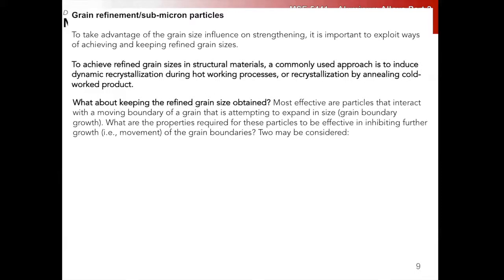It recrystallizes by what's called continuous recrystallization. So you have to have severe plastic deformation that rotates all the subgrains until they form a high angle grain boundary. But because of the high stacking fault energy, we never build up enough stored dislocation content to undergo a traditional nucleation and growth for dynamic. It recovers too easily. So it's a different mechanism.